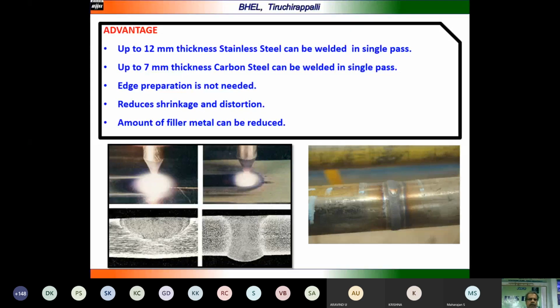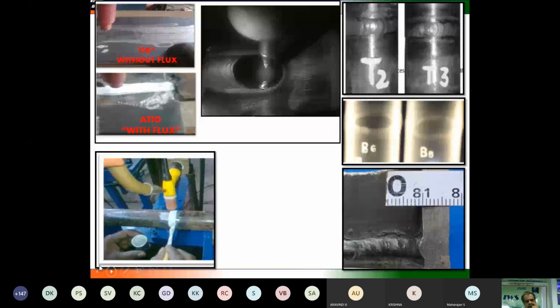And you can see here is TIG welding without flux, and here it is with the flux. The flux is a small powder which can be mixed with acetone, and then it can be applied over the surface, and there should be no metal surface to be seen. That is the only thing. And then you can start the welding, do the welding continuously.